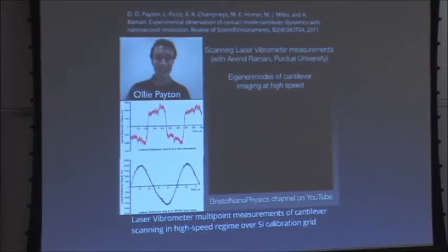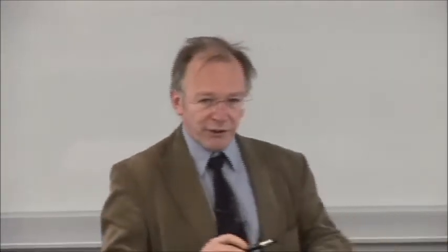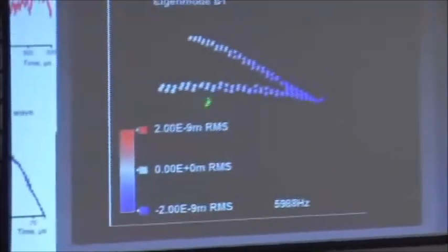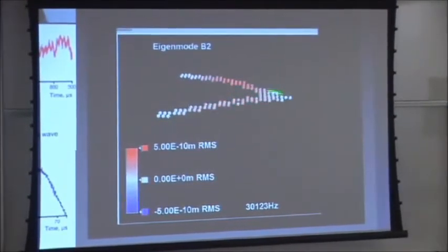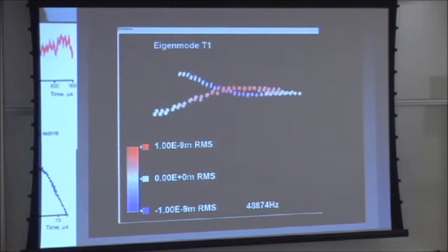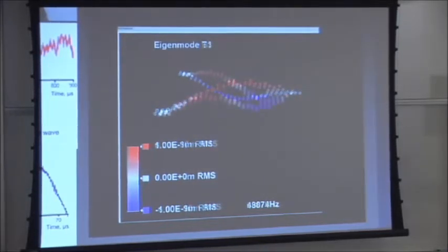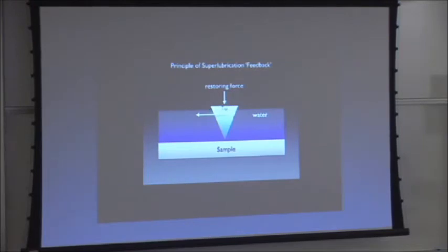So there's a clue. That's a viscous effect. Our hypothesis was that when we went fast enough, the tip lost contact with the surface, lifted off the surface and felt only the viscous forces as it moved through the liquid. Ollie did a lot of work measuring. This is real data, taken with a scanning laser vibrometer, so we can measure the behavior of the cantilever at all these points. You can see these dots are all the points it's been measured at, all the different modes as we go over a step. So we've analysed what's going on in the cantilever, and we've measured its height. We believe this is what's happening: as the probe moves through the liquid, we build up a hydrodynamic pressure on either side, and that lifts the tip off the surface, which lowers the pressure, and so we have an equilibrium position of the tip above the surface.